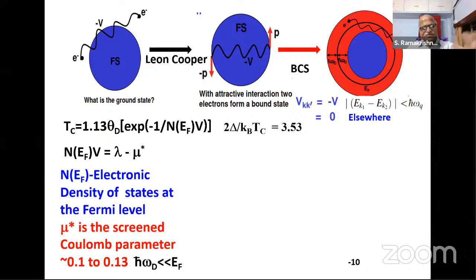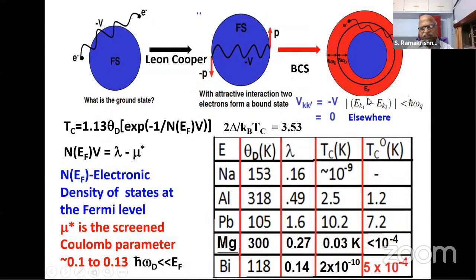So forget about this equation right now. Just apply this equation to the system which we have. So let's say it's sodium. We know that the Debye temperature of sodium is 153 Kelvin. So the lambda is 0.16. So if you plug in these values into that expression which I gave you, you get 1 nanokelvin for TC. Of course, nobody is interested in sodium, so nobody has ever cooled it to such a low temperature to see whether it is superconducting or not.